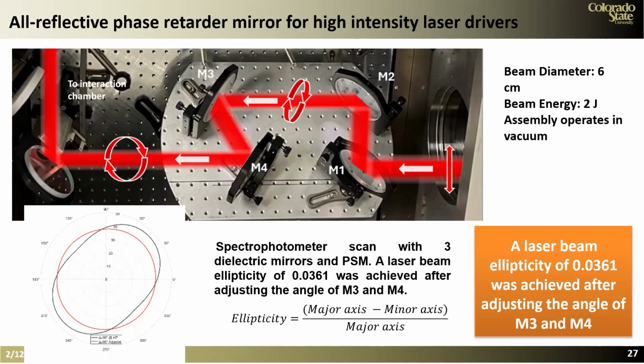So what we did is we made a mirror that can phase shift the S and P components of the incoming light. We come in with linearly polarized light, and this is the mirror that we made. Out of this mirror, we have elliptically polarized light, and then we designed the coating so that after the light bounces over these two mirrors and goes into the chamber, we end up with circularly polarized light. It was used in an experiment in which electrons were being steered by the circularly polarized light.